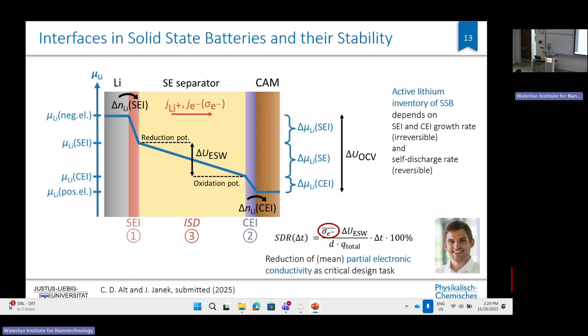The OEMs define that a lithium-ion battery should not discharge more than 2% per month. In fact, they are better, often better than 0.1% per month self-discharge. So quite good, even for long-term storage. For lithium-ion batteries, the self-discharge is very difficult to estimate, because it's due to complex redox shuttles in the liquid electrolyte. Lots of stuff can move between the electrodes across the liquid electrolyte. In a solid-state battery with inorganic solid electrolytes, only electrons can cause an internal short circuit. So the question is, what is the minor electronic conductivity of the solid electrolyte? And that is not well treated and not so well known, I would say.